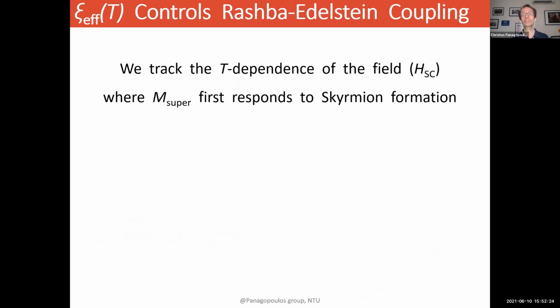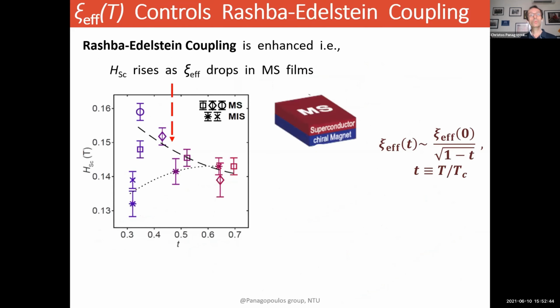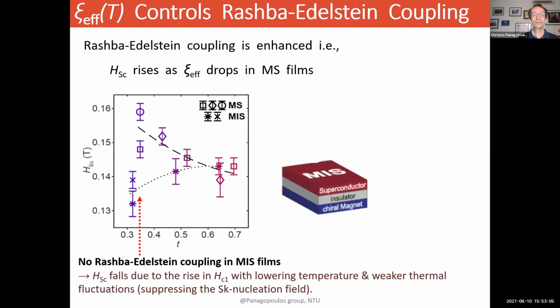So we can track the temperature dependence of the field where the superconducting component of the magnetization first responds to skyrmion formation. And with this, we can actually look at where exactly Rashba-Edelstein coupling switches on or off. So what we find is that the Rashba-Edelstein coupling is indeed enhanced. In other words, the field where the superconductor responds for the first time to the formation of skyrmions rises as the effective superconducting coherence length drops in the MS films. Whereas there is no Rashba-Edelstein coupling when I insert an insulator and I decouple my superconductor from my magnet.